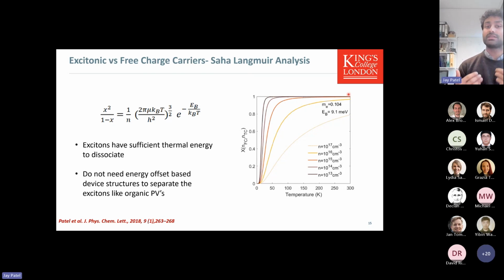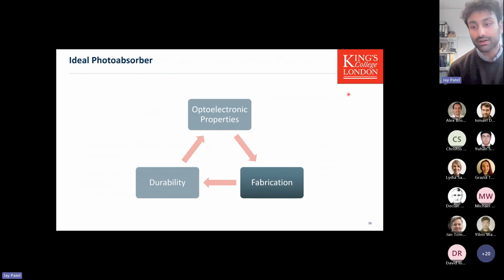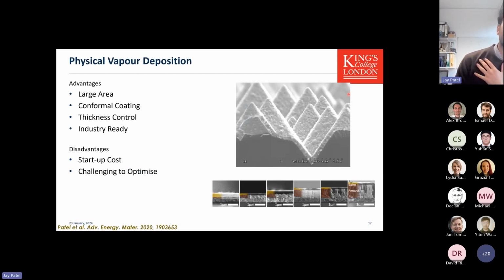How does it do when we actually start processing it? And so then we come down to fabrication. Usually, people say you can use a solution-based method, or inkjet printing, or you can use a dry method. And what I specialize in is the dry method. The advantages of the dry method, physical vapor deposition, is that you can coat large areas, you can do a conformal coating, and you can really tune the thickness of your absorber.